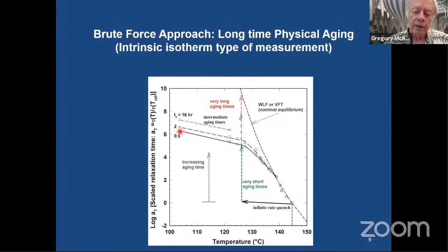So at a half hour, even though I'm 35 or 40 degrees below TG, the relaxation time is shorter than when I've aged it for 16 hours. Okay, and in this case, it's a whole order of magnitude different. And here we see the question that I'm asking is, if I age long enough, do I get to the VFT curve, or does it stop somewhere in between?